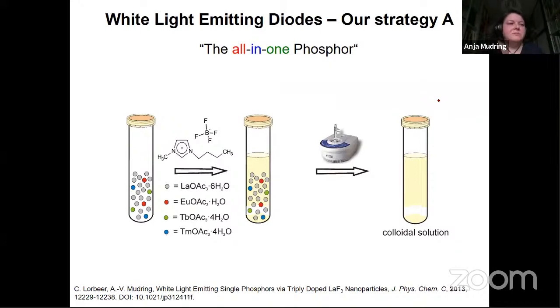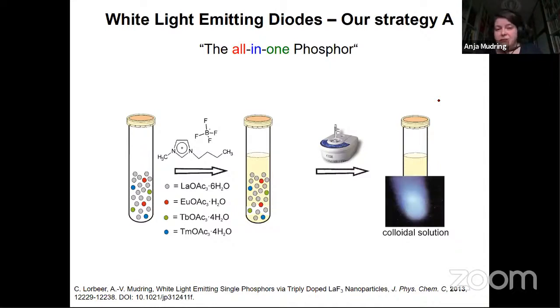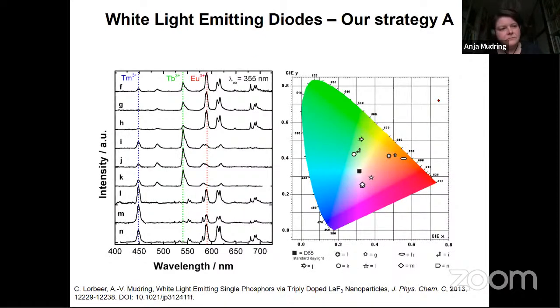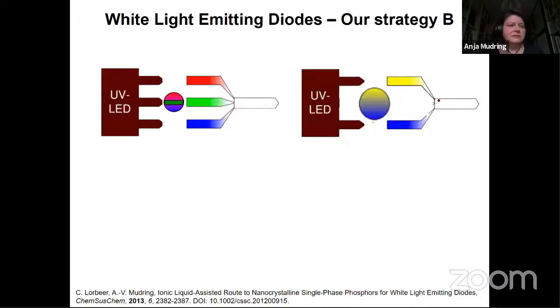So it requires some sort of tuning to get the right concentrations and to get the right rare earth ions. When it comes to synthesis, it's rather simple, because we can use the approach we had before with the microwave irradiation in the ionic liquid. You take europium for the red, you take terbium for the green, and thulium for the blue. Take the proper amounts, irradiate, and you get something that emits in nice white light. And really, depending on the concentration of the rare earth ions, you can hit exactly the white light spot. So that's good. But still, you have to play around with 3 different ions.